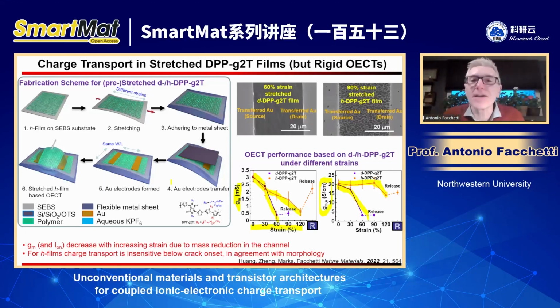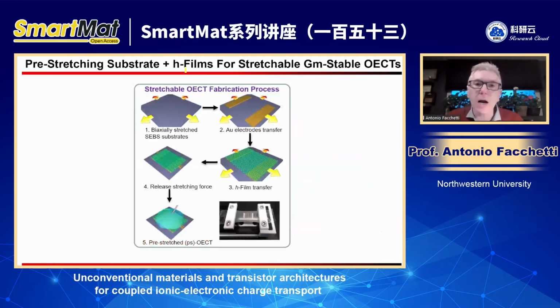But this is not useful in real devices, right? In real devices, you stretch the whole device. You don't stretch just the semiconductor and you laminate it. So you want to have a stable current when you stretch the device, not a normalized current. In order to do that, what we did is we used the honeycomb film on a pre-stretched substrate. Basically, we take an elastomer, we stretch it, we put the source and drain, we put the semiconductor, and then we release it. So everything goes compressed. Then we finish the device, and then we start stretching.